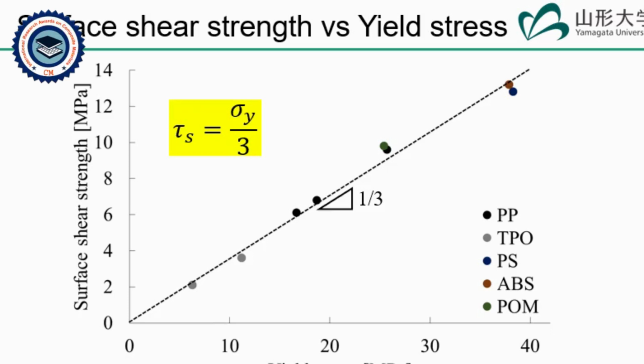Considering the stress state under which this relation holds in the von Mises yield condition, the stress produced in the overlapped short beam shear test was regarded as a pure shear stress, which indicates that the tests conducted for this study were evaluated in accordance with expected principle. These results indicate that only shear stress is applied to the surface of the molded product by performing the overlapped short beam shear test.